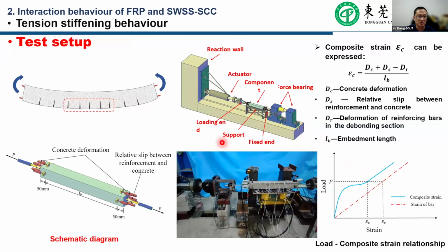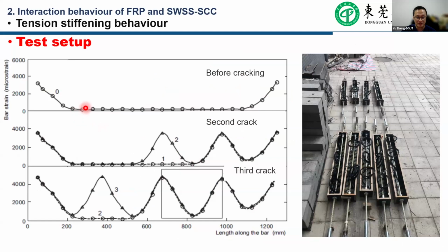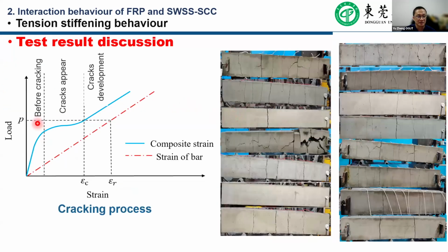And in the second stage of this study, we try to extend this research to study the composite behavior or the tension stiffening behavior of the FRP reinforced self-compacting concrete. We try to investigate the composite strain, which can be expressed by this formula. We compare the composite strain with the strain of the FRP bars, and investigate the cracking behavior of these specimens subjected to direct axial forces. This second stage investigates the whole test process before the cracking appears and the cracking development. This is the failure mode in our study.